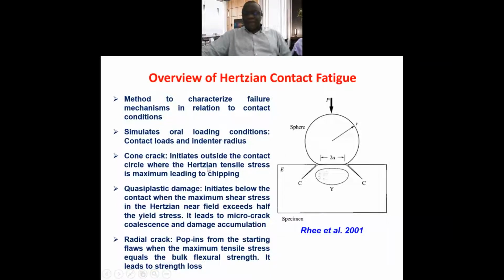So what are the types of cracking system? One is the cone crack. It initiates outside the contact circle, where the Hertzian tensile stress is maximum, leading to chipping. The crack can propagate this way, and then this part can be chipped off. Then quasi-plastic damage initiates below the contact, where the maximum shear stress in the Hertzian near field exceeds half of the yield strength. This can lead to microcracks, coalescence, and damage accumulation. The other one, and the most dangerous, is the radial crack. It pops in from the bottom surface when the maximum tensile stress equals the bulk flexural strength. This can lead to loss of strength.